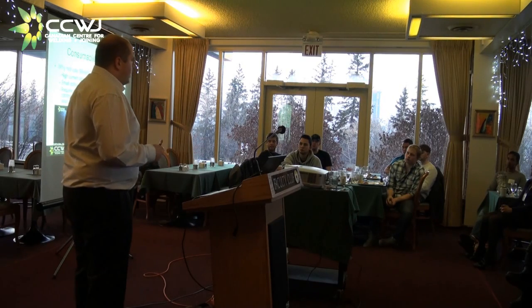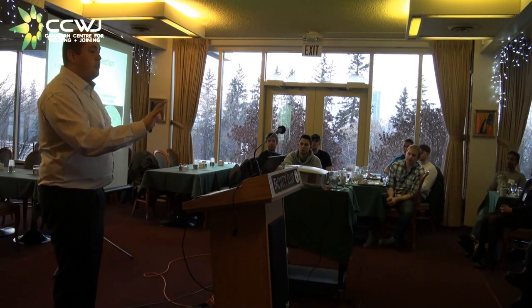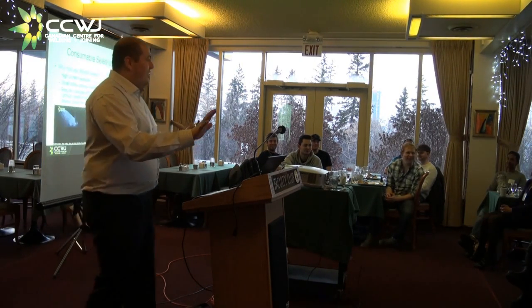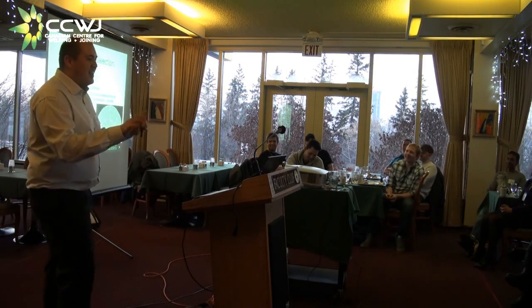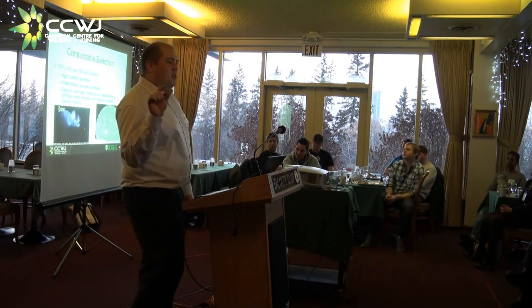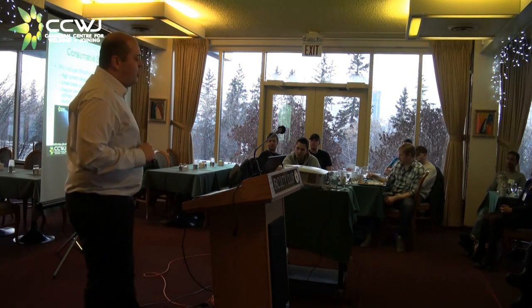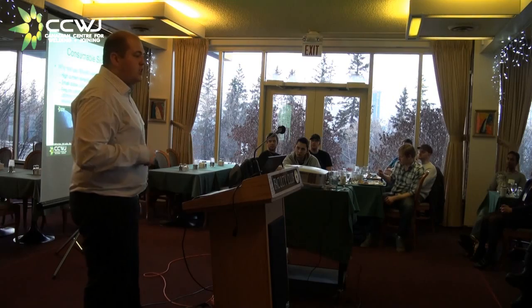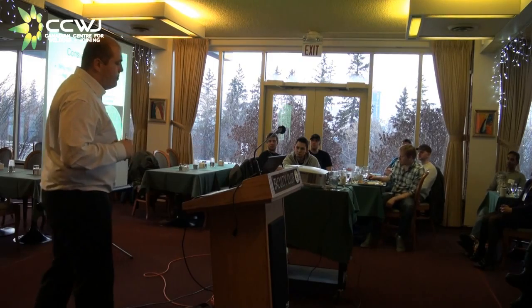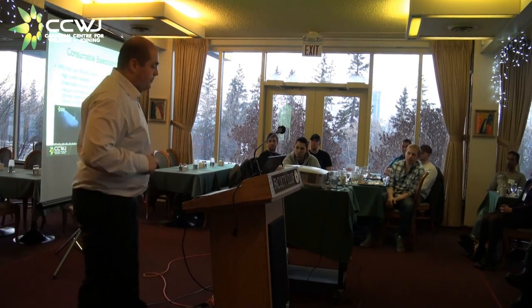One thing to know about these is you need to have the best welder, not your best welder working on these, but the welder that listens the best. These wires weld ugly, they sound ugly, but that's the way they have to be done. If there's welders in the room, I have nothing against you. But if they tweak the knobs to make it sound a little bit better, all the expensive tungsten carbide that you just bought is going to disappear. It's either going to get lost during transfer, which we'll discuss in a bit, or it'll dissolve because you turn the heat up too much.